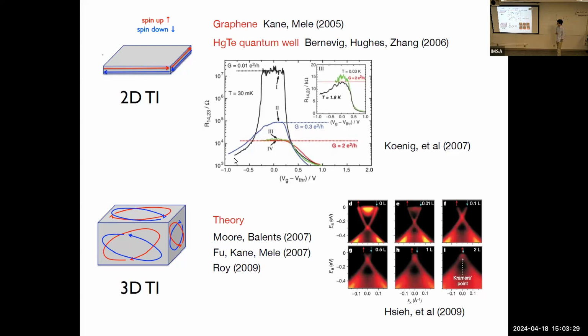After that, people started thinking about 3D versions of them, and there were three groups which developed the math for the theory of 3D topological insulators independently, around 2007. And then the first observation of this topologically protected surface state was done by David Hsieh in 2009. This is an ARPES picture of the band structure and the electron population here, and you can see this nice Dirac cone. And this is all good, but for experimentalists to actually verify that something is quantized or topologically protected, one should be able to measure its response function, not just look at the band structure, but also try to measure something in the lab and see if it's actually giving what mathematicians and theoreticians have predicted it to give.